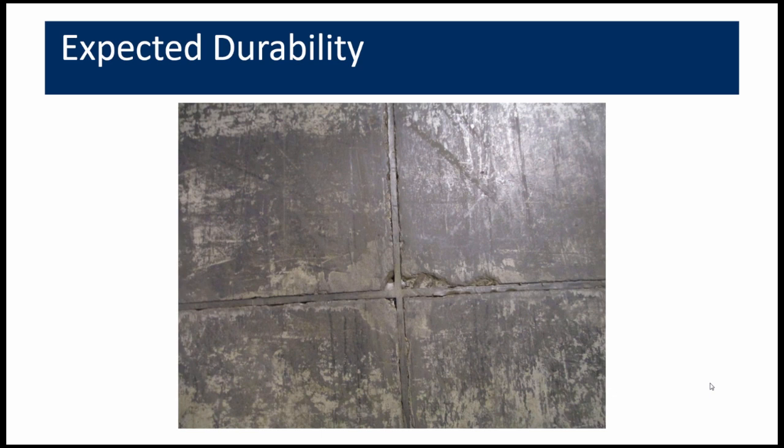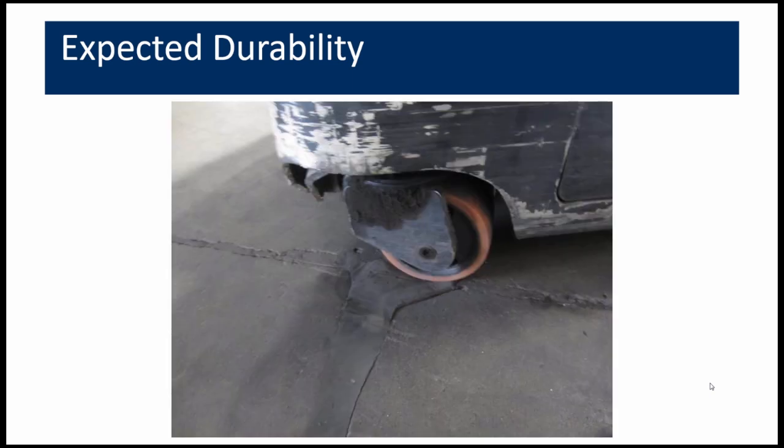This next slide shows joint repairs that I designed probably 12 years ago. One of the things that we didn't do was slab stabilization. So although the repairs are still there and kind of helping, in hindsight, I think some slab stabilization was merited. This is what can happen. Those joints and edges will simply deteriorate due to the rocking and the movement. We really need our slabs to be static, so lesson learned there.